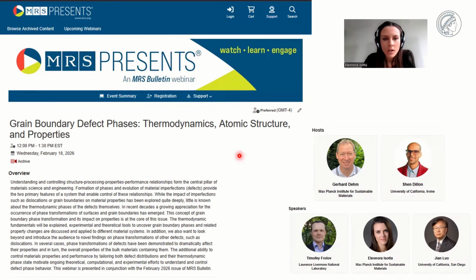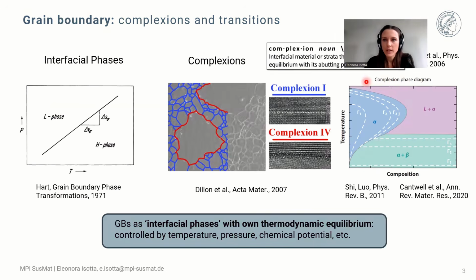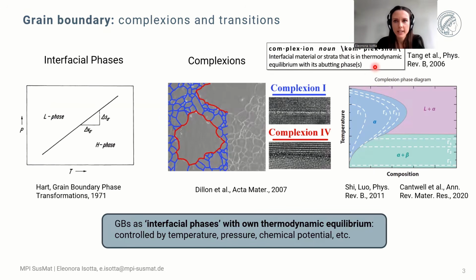When we think about grain boundaries, we have come to the understanding that they can behave as phases. The idea of grain boundaries behaving as interfacial phases dates back to the 70s, when Hart first proposed that according to some thermodynamic conditions, for example pressure or temperature, the grain boundary could undergo transitions from one phase to an additional phase.